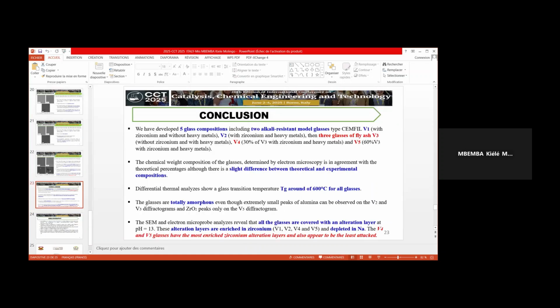So to conclude, we can say that we have developed 5 glass compositions, including 2 alkali-resistant model glasses, type CEMFIL, V1 and V2, and 3 fly ash glasses, V3, V4, and V5. The chemical composition of the glasses determined by electron microscopy is in agreement with the theoretical percentages, although there is a slight difference between theoretical and experimental composition. Differential thermal analysis shows a glass transition around 600 degrees for all glasses. The glasses are totally amorphous, even though extremely small peaks of alumina can be observed on the V2 and V3 diffractograms, and zirconium oxide peaks can only be seen on the V5 diffractogram.